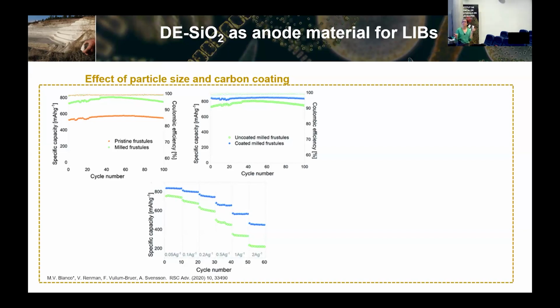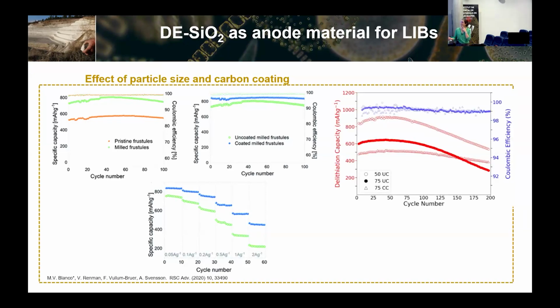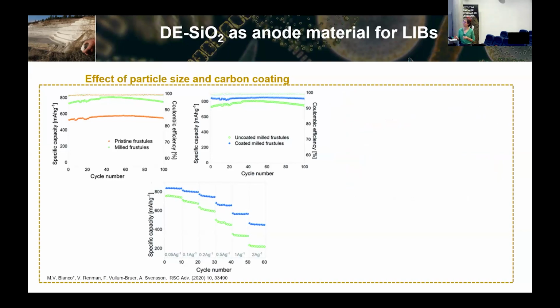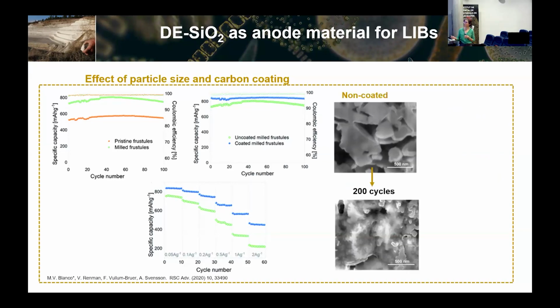And there is a reason why we didn't publish what happened above 100 cycles. It's because after 100 cycles, the capacity starts to decay dramatically. So 100 is like the nice number, and then everything goes wrong. We tried to see why we have this capacity loss after 100 cycles. Doing some investigations in the non-coated material, we can see how the nice smooth surface of the diatomaceous earth was totally lost. This is typical behavior of silicon, this particle disintegration that silicon has.